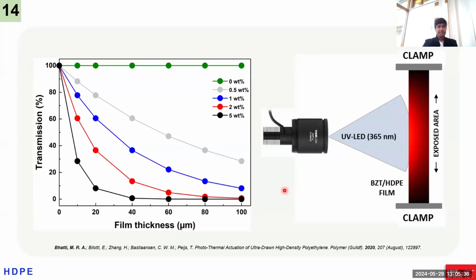That gives us a base to think that we should create a thinner film, because at a thinner film level, maybe we will be able to eliminate the thermal gradient and generate a higher actuation stress. But the problem with HDPE is that we cannot draw the films beyond a certain draw ratio. We tried up to a draw ratio of 20, but at that draw ratio, microvoids were generated, especially in the direction perpendicular to the chain orientation direction, which in turn reduces the transparency of the film and also the strength of the film.